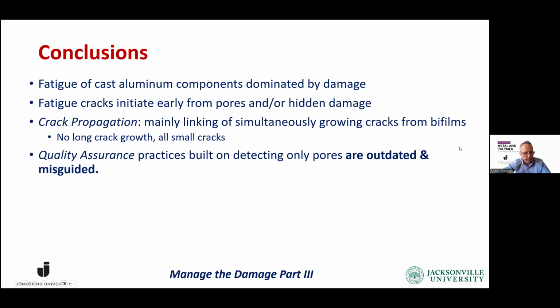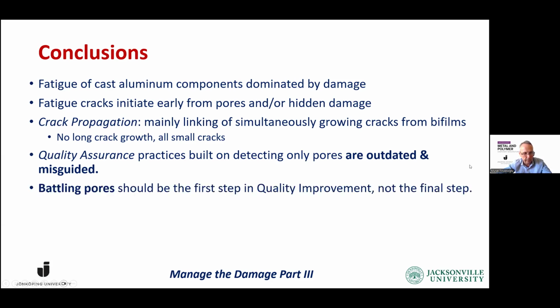So at this time, being a certified quality engineer, I can easily say that the quality assurance practices built on detecting only pores are outdated and misguided. Eliminating pores should be the first step in quality improvement, but not the last step. You've just taken the first step in climbing the mountain, but there's a whole big mountain left to climb. So you have to quantify the damage to manage the damage, and we've given you a tool that you can start using now from your tensile tests.